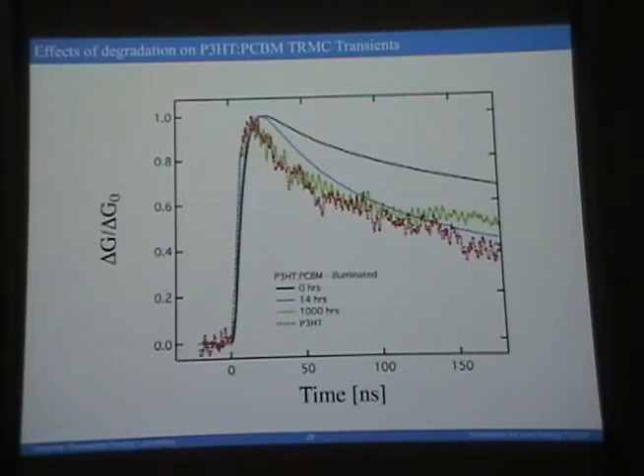But here is some microwave conductivity data for material systems that have been prepared as a witness to the device. So the two systems were prepared, one was a device, one was just the material. And so here is a signal from this blend when it was first made. And as you irradiate the sample, we know the devices get worse and worse and worse. And you see the microwave conductivity transients drop off. And right after about 1,000 hours, they look very, very similar to the neat polymer. Why is that? Well, I'm going to tell you it's because the PCBMs aren't clustered.